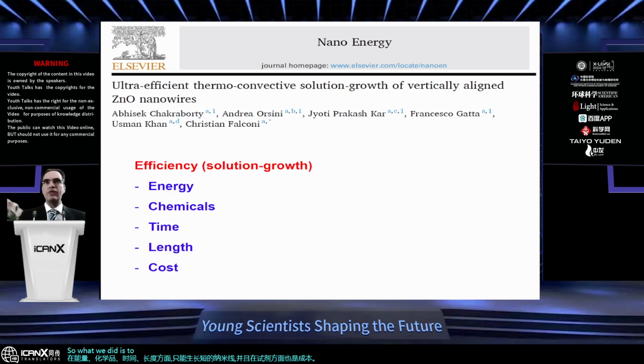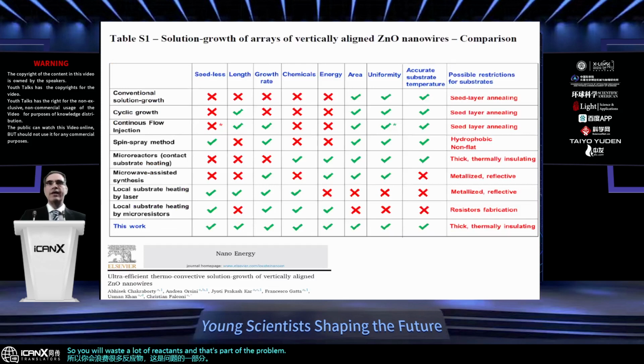So what we did is to try to change the conventional wet chemical procedure that consists in heating the entire container of the nutrient solution. Because if you do that, of course, there will be reactions even in the container far from the substrates. So you will waste a lot of reactants, and that's part of the problem. So we reviewed the many approaches that have been proposed in the past to improve this efficiency in some ways, but we could not find a technique that was good from all possible points of view.